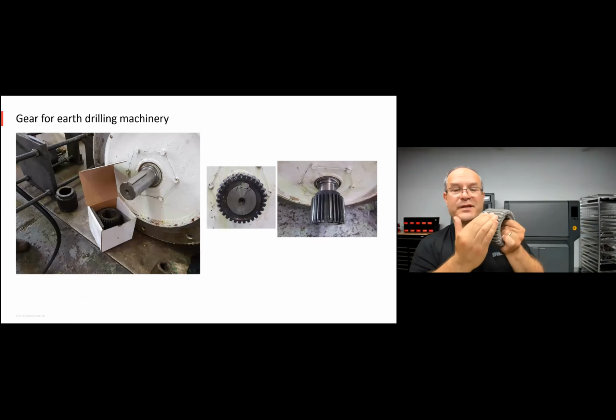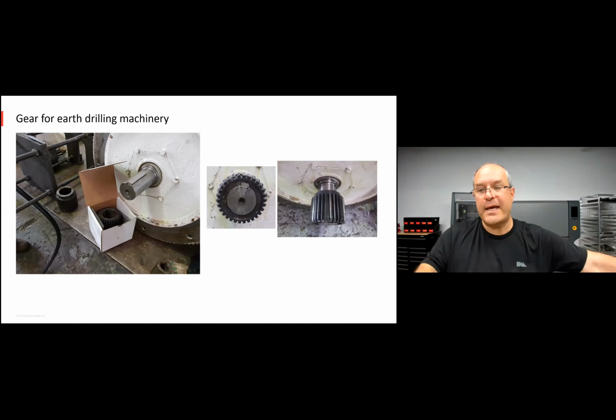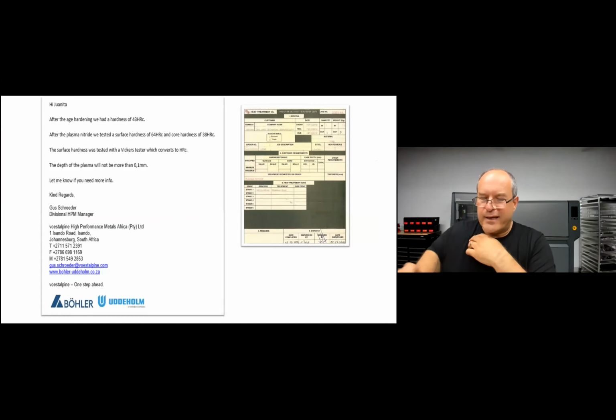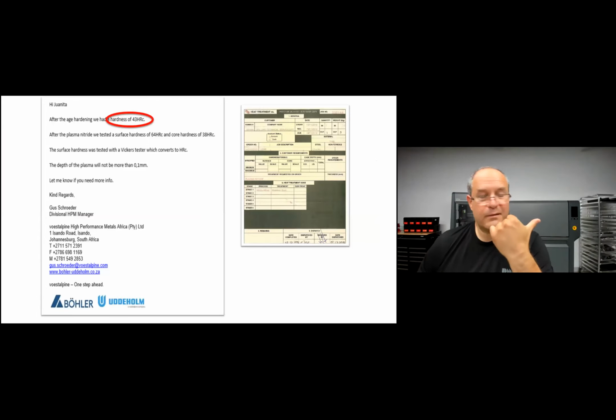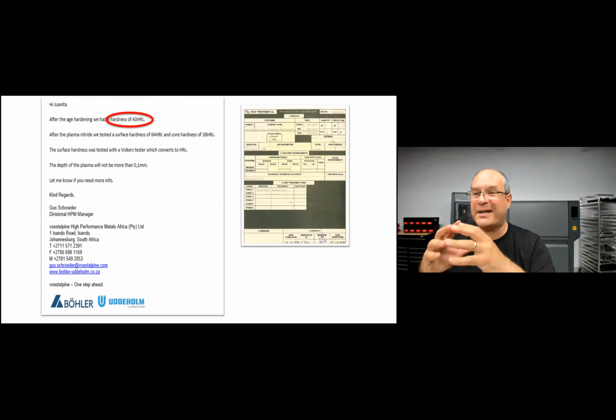It's actually quite important for this gear to be very hard, in terms of Rockwell C. It doesn't spin fast, but it's important. It transfers a lot of forces. And so here's a certificate. I'll point out a couple things. First of all, the part started as a 17-4 part coming out of the furnace fully annealed. So that means 22 to 25 Rockwell C. After age hardening, the entire gear got to 43 Rockwell C. Quite hard. But that's not enough.